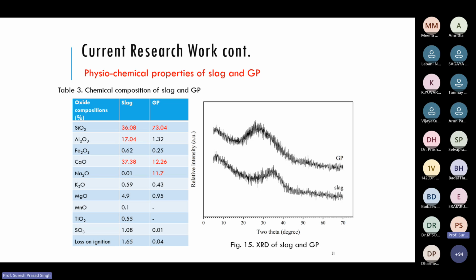Both are amorphous. There are no remarkable peaks. There are only two humps there, and these humps show that the material is in the glass stage, or amorphous stage. There is no crystalline structure. And as I told you, the aluminum silicate material should be in the glassy phase, so that will give you better geopolymer. So both the materials, as found from the XRD, are highly glassy or amorphous.